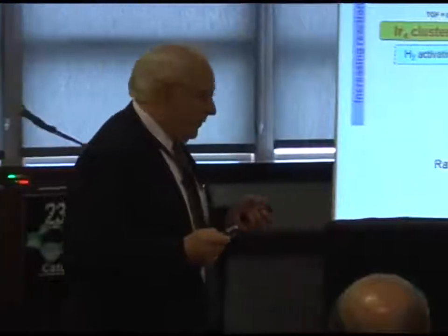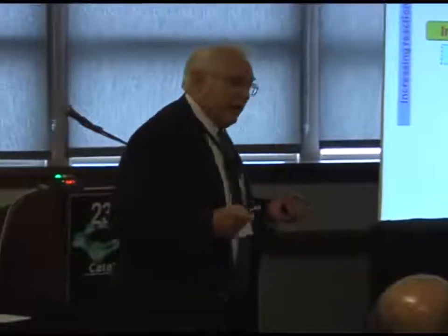And so here are the results. So start here arbitrarily. The mononuclear iridium complex on MgO, if we change support to the poor electron donor, we get a 20-fold kick in activity. Then if we go from mononuclear to tetranuclear, we get another little kick in activity. If we go this way, mononuclear on MgO, go to clusters on MgO, we get this kick, and then, of course, we get that kick. So we've resolved the separate effects of the support as a ligand, an electron donor ligand, and the nuclearity of the metal species.